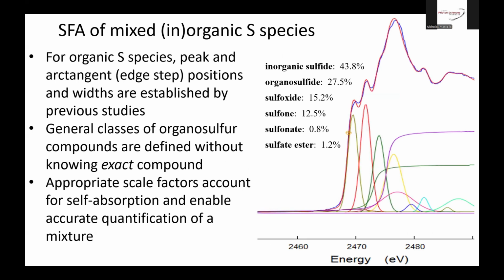So this is a complicated example, but it's a good one because it was successful. This is a mixture of inorganic and organic sulfur species. So the spectrum looks kind of hard to interpret. If you just saw that spectrum, you wouldn't really know what was going on. But we know about this particular material, by using point spectra, that there are some organic spots, there are some inorganic spots. We identified what the inorganic spots are.